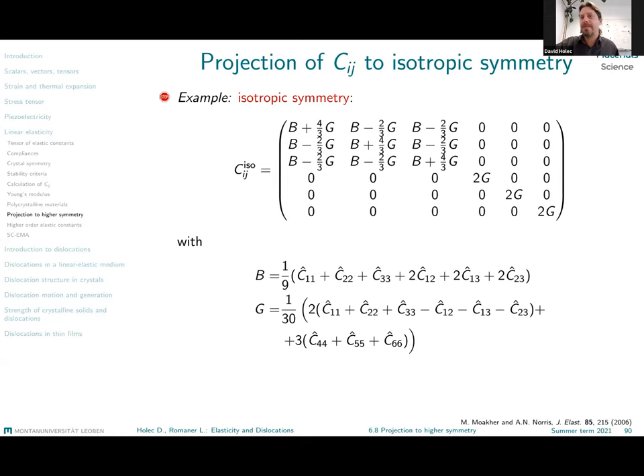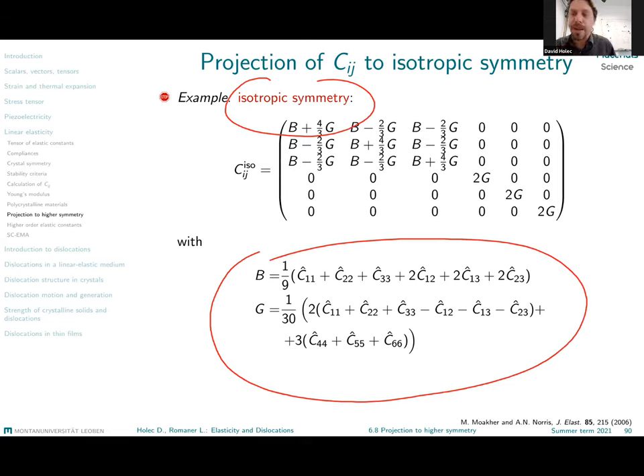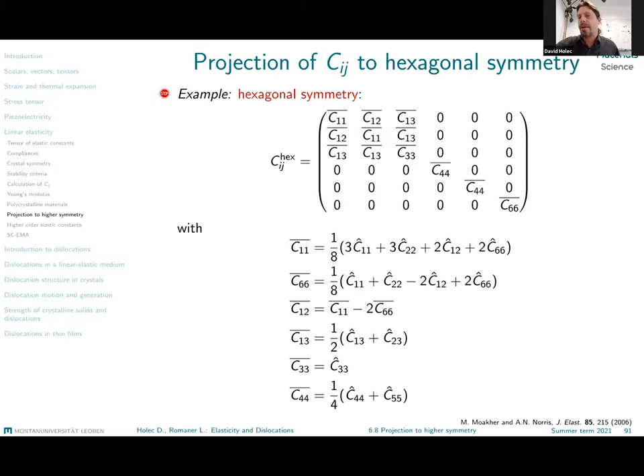So when we see, for example, for isotropic symmetry, the values that you need to describe the bulk modulus and shear modulus, the two moduli describing fully the elastic properties of an isotropic material, are obtained with much more complicated formulae. Or even more obvious, this becomes for hexagonal materials, where one would be tempted to say that the C11, which is the same as C22 for hexagonal materials, is simply the mean value of C11 and C22 that you get in your non-hexagonal symmetry matrix. And you see it is not.